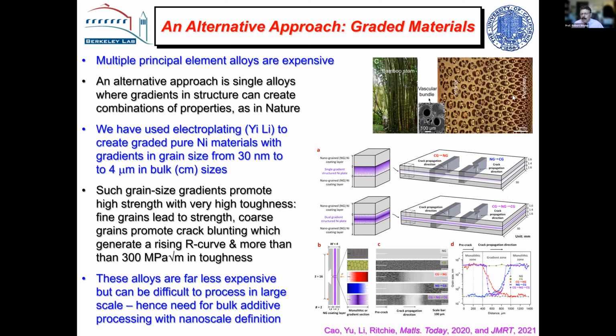Nature does this all the time. It's difficult for us to put gradients in. It's kind of costly, but we've done this with a technique that Yi Li did for us at IMR in Shenyang using electroplating with nickel. And we've generated gradients from a coarse grain, which is about 4 micron, to a fine grain, 30 nanometers, but in bulk sizes. People have done it in teeny sizes. We've done it now in centimeter dimensions. And what we find is we can combine strength and ductility seamlessly with these gradients.